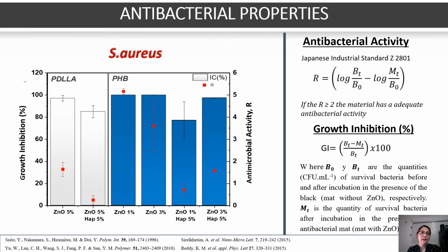In the figure, the antibacterial efficiencies of the materials evaluated with S. aureus strains at different concentrations of nanoparticles is presented. It is observed that the incorporation of hydroxyapatite produces a decrease in the inhibition of bacteria. A study of the effect of hydroxyapatite on S. aureus strains shows that hydroxyapatite promotes bacterial growth, which is why hydroxyapatite would be producing a kind of screen effect in the ternary system, which interferes with the antimicrobial performance of zinc oxide.